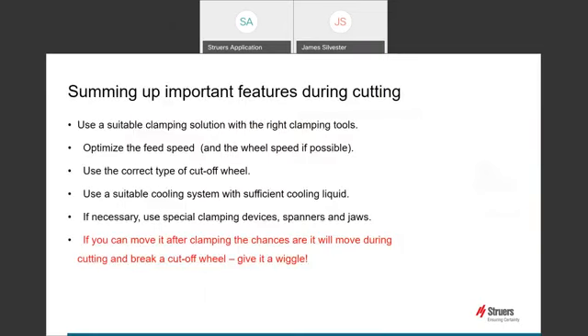In order to avoid most problems during materialographic cutting, the following rules of thumb should be adhered to. Use of a suitable clamping solution with the right clamping tools or jig. Optimize the feed speed and the wheel speed if possible. Use of the correct type of cutoff wheel. Use of a suitable cooling system with sufficient cooling liquid. And if necessary, the use of special clamping devices and jaws. And remember, if you can move your sample after you've clamped it, the chances are it will move during the cutting and break a cutoff wheel. If in doubt, give it a wiggle.